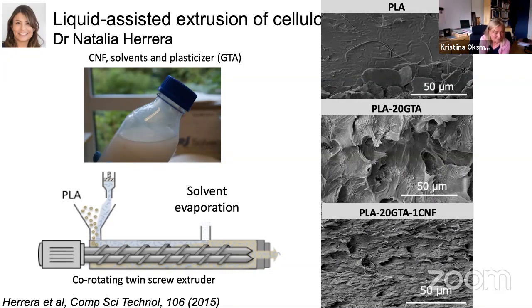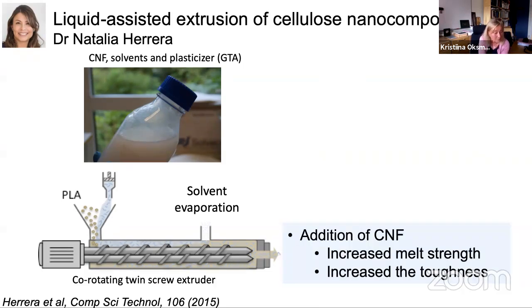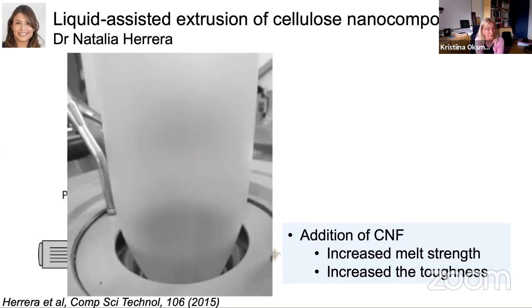And maybe you are now wondering why we are not just using this 20% plasticizer, because it's making the material tougher. But the problem is that this plasticizer is affecting the melt properties of the polymer, and it's not possible to make blow molding of plasticized PLA. It doesn't have any melt strength. So adding 1% cellulose nanofibers actually could improve the melt strength, and it was still having a good toughness in the material, and we could make this type of bags.